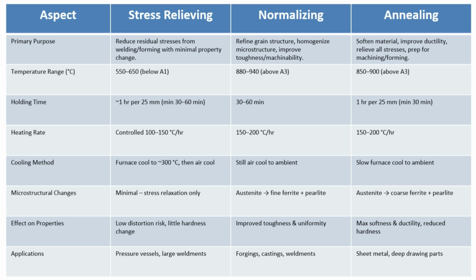Say these are the three processes: stress relieving, normalizing, and annealing. The different aspects we're talking about. So the primary purpose of stress relieving is to reduce residual stress from welding and forming with minimal change in the properties. The temperature does not reach the transformation temperature to cause phase changes. So there is no change in the property as such other than relieving the stress. Normalizing refines grain sizes, homogenizes microstructure, and improves toughness and machinability. As I mentioned, it improves toughness, ability to absorb shocks and impact.